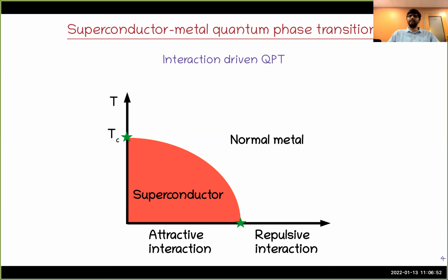For instance, if there is, let's say, an attractive Hubbard model at a theoretical level, then because of attractive interactions, you can have a superconductor even at T equals 0. If you now increase your interactions and make them repulsive, then you will go to a Fermi liquid normal metal. So again, you have a quantum phase transition between a superconductor and a normal metal. Typically, given the theoretical progress in superconductivity, nothing really surprising or exotic seems to happen in such a quantum phase transition between the superconductor and a Fermi liquid metal. These are all well-behaved phase transitions, at least in the models that have been studied so far, and you get just normal Fermi liquid kinds of instabilities and Landau kinds of phase transitions.